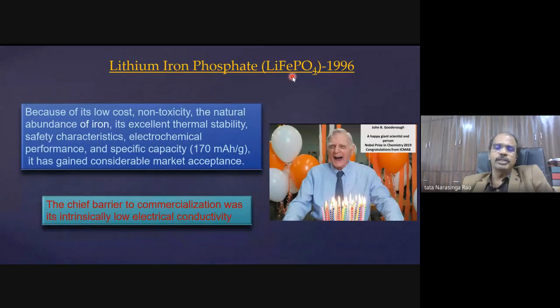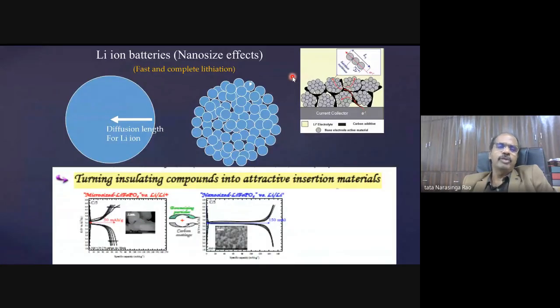happened when nanotechnology came? So in nanotechnology, what happens is when you have a big particle of lithium iron phosphate, because it's an insulator, the diffusion length of the lithium when it goes into the particle is long; it has to swim all through this diffusion length. But if you have nanoparticles, for the same volume, the diffusion length is small. So in each particle, the lithium goes in and comes out very fast.